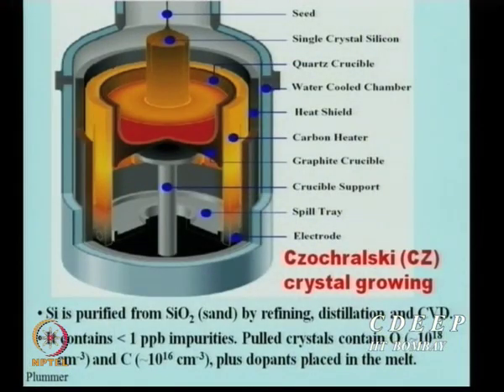Essentially this is just pulling up the rod from the melt. There is a rate of pulling, and also during pulling we also rotate. Many times there are some reactors in which the whole melt was rotated, but the melt is very high density material and at times it breaks the crucibles. So nowadays only the rods are rotated. These are the two methods — pull rate and rotation speed — by which we control growth as well as impurity uniformity.